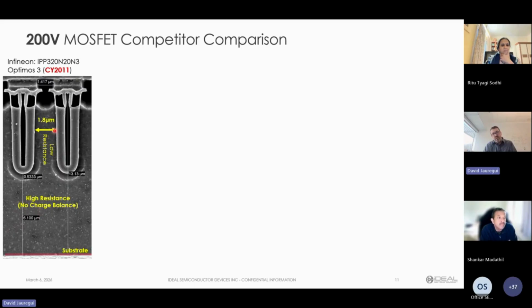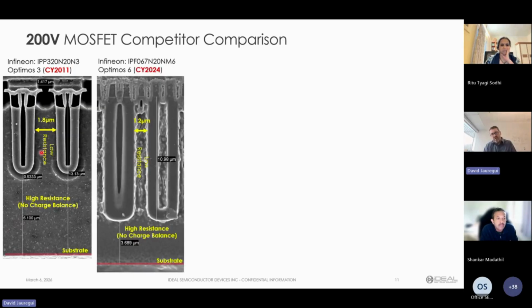And so this was the leader back in 2011, and you can see their mesa width is about 1.8 microns wide. And this region, which is used for that blocking function, is about 2.5 microns wide. So actually, they're at less than 50% utilization of the silicon area. And then in 2024, they released their 6th generation technology. Again, this is Infineon. And they went from having a 1.8 micron mesa to a 1.2 micron mesa. And so clearly, they were able to improve the resistance per unit area by heavily doping this area, but you can clearly see geometrically they're starting to reach these manufacturability limits. And then once again, this is that same region that's used for blocking, not used for conduction. This is a field plate. And so all the current's got to funnel through this region and then go through this higher resistivity material.